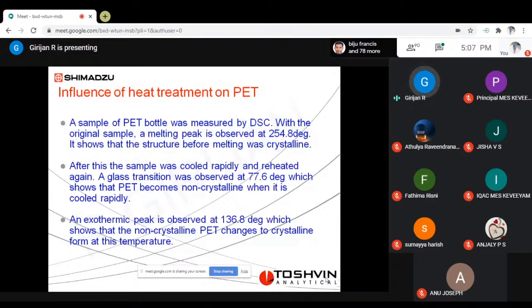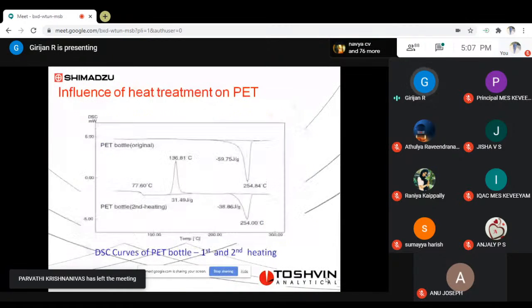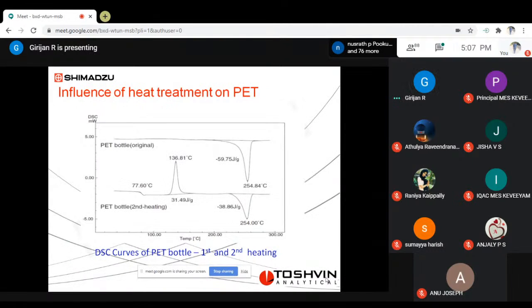And finally, an exothermic peak is observed at 136.8 degrees, which shows that the non-crystalline PET changes to crystalline form at 136.8 degrees. So you can actually study the heating, rapid cooling and reheating process on a polymeric material, and from the corresponding thermogram you get a lot of information.